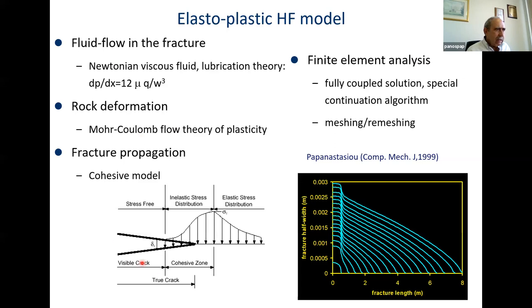This was the fracture propagation criterion, but at the same time, we calculate the path-independent J integral, from which it was possible to calculate the effective fracture toughness during propagation. So the fracture was propagated based on the cohesive model, but the J integral was able to give us the effective fracture toughness. Finite element analysis, fully coupled solutions, meshing, remeshing to do long propagations. And you can see in the pictures here, the fracture profile is just a quarter of the fracture due to symmetry. It starts from here and it propagates.